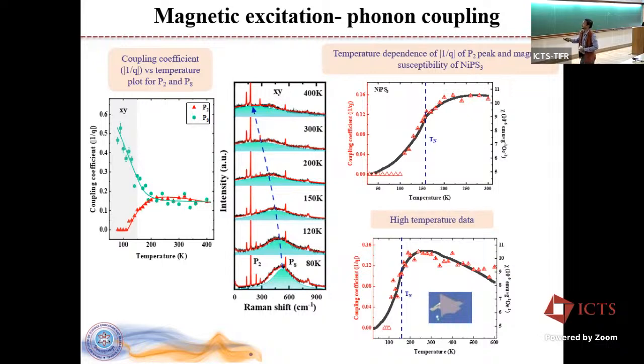At low temperature, this peak is far away from the magnon peak, hence there is no coupling. But as the temperature rises, it approaches and goes almost to P2, and that's where the coupling becomes more and more. It's like a coupling between a discrete state and a continuum state. The continuum is basically the magnon signal here. There were discussions whether it's really because of the coupling with the 2 magnon or something else. The paper is still under review. We got the report and it looks positive.